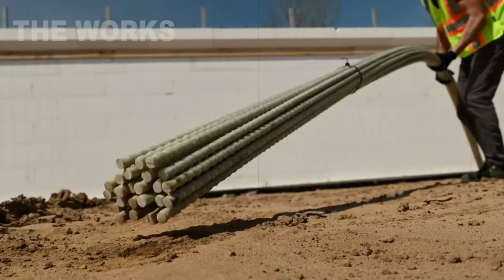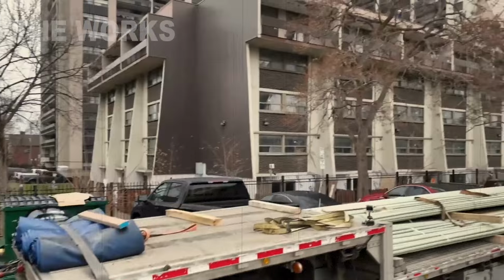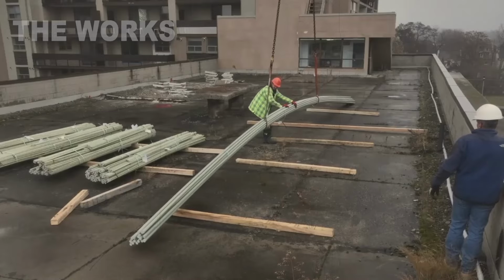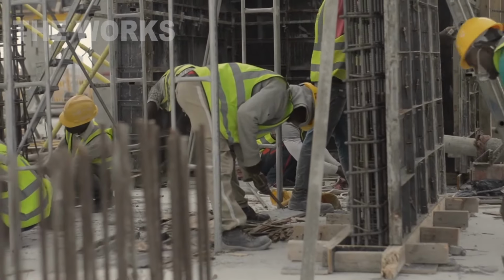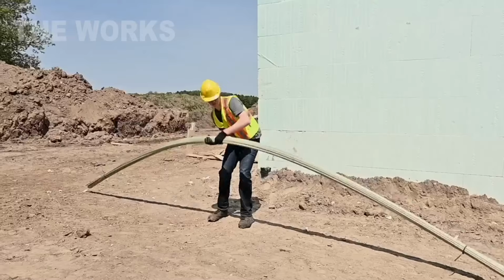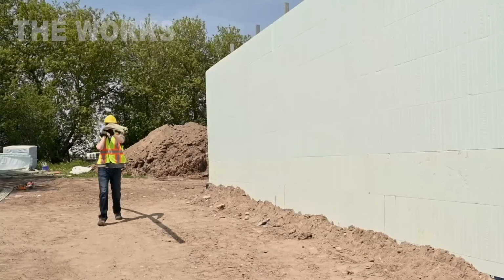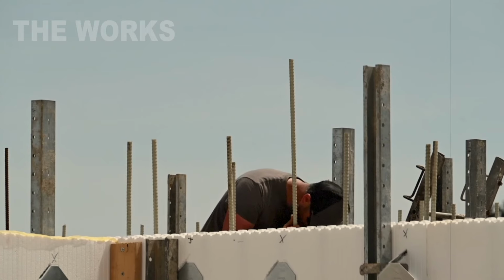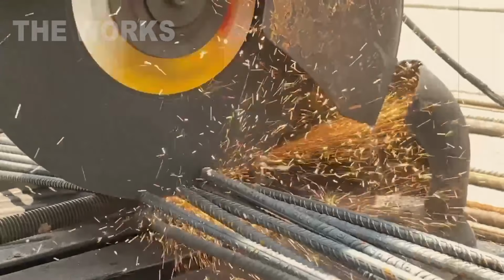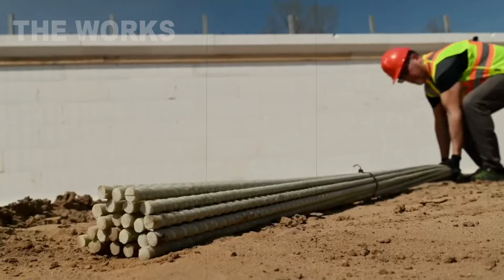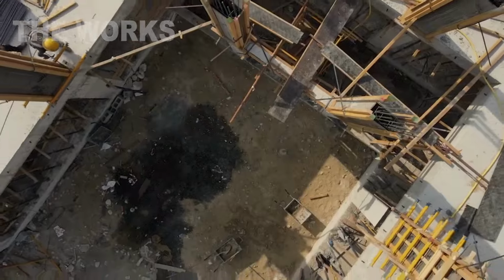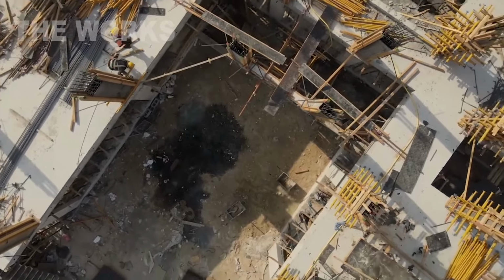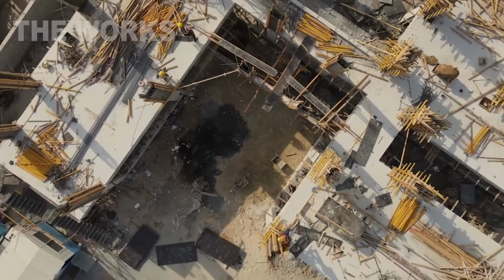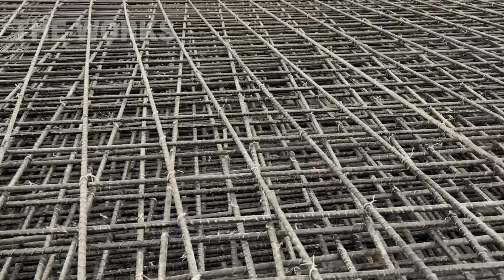On the construction site, 2 workers can easily carry entire coils of GFRP rods, whereas moving steel requires a crane. This represents a colossal saving in logistics and labor. Second is strength. And here, GFRP steps into the ring and knocks steel out in the first round. Its tensile strength is approximately twice that of standard steel rebar. This means that for some structures, a smaller diameter rebar can be used, saving even more on weight and volume.